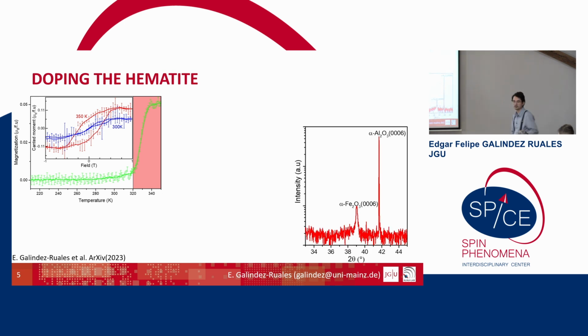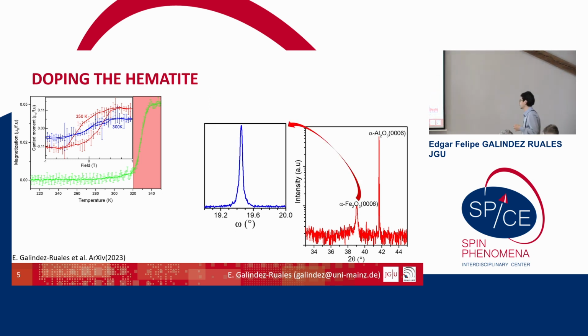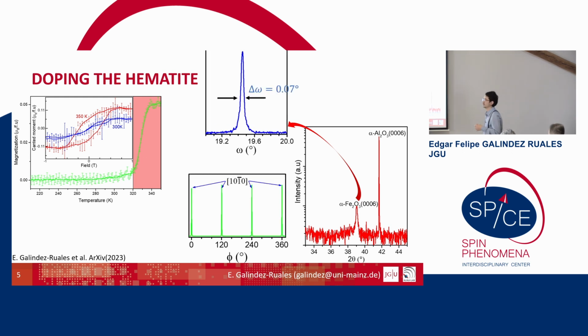So we measure how well grown our samples were. We have a highly epitaxial sample, and then we measure the rocking curve. The rocking curve was around 0.07 degrees in omega, so that was quite good. And then we measure an in-plane scan, trying to identify where the crystallographic A-axis that I mentioned is. So we identify the crystallographic threefold symmetry that I wanted in my material, and I marked the sample really well, where my A-axis was.